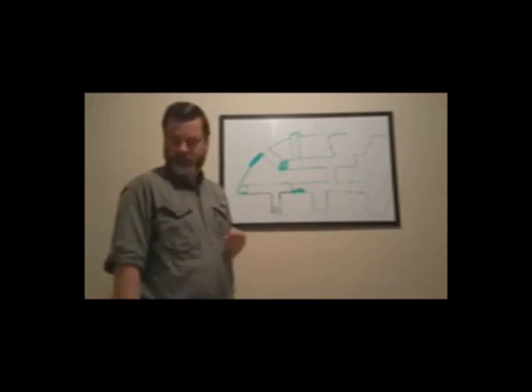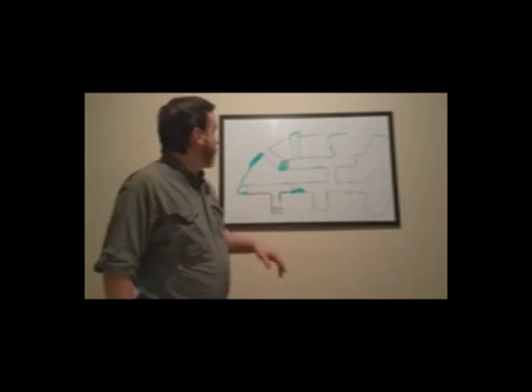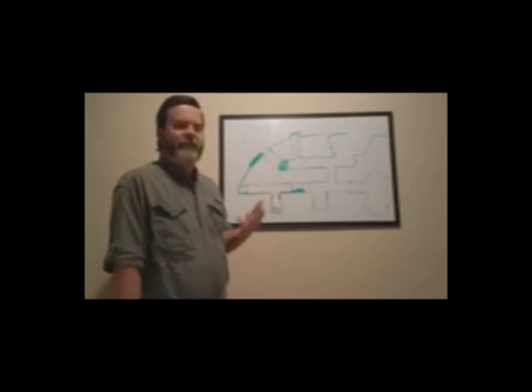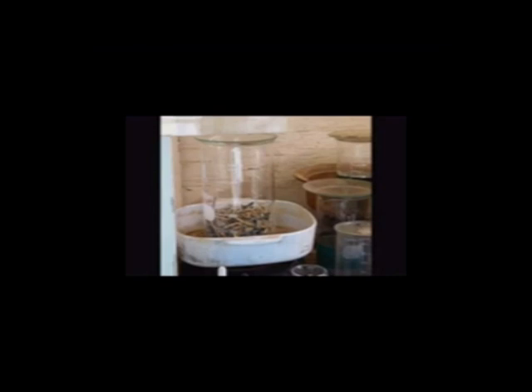Acid comes over. Now, if you look at the boiling flask, you can see a large hunk of sodium sulfate. The problem with all that sodium sulfate is that it may trap reactants inside of it. I'm not sure if it's a significant problem, but one of the methods I've seen for making nitric acid is to crystallize out the sodium sulfate before distillation. I'm going to test that and mix another batch of 43 grams of sodium nitrate and 75 grams of sodium bisulfate in 150 milliliters of water.